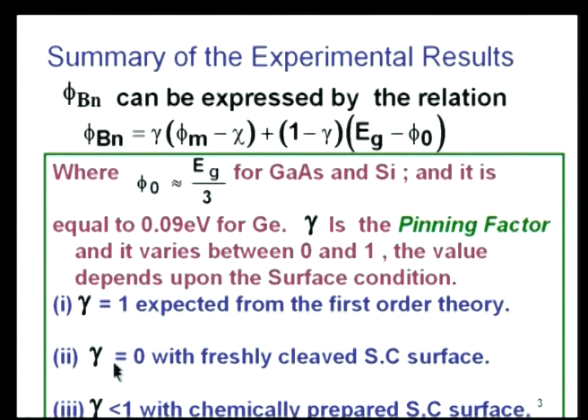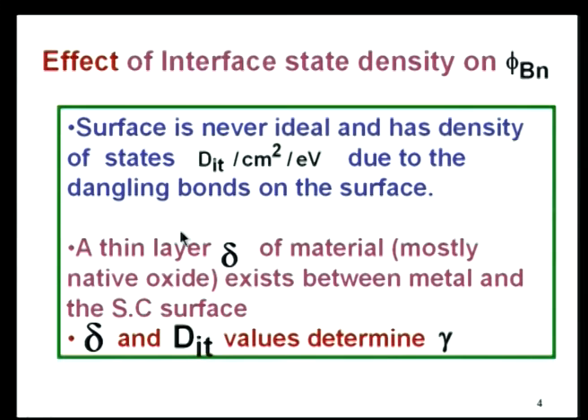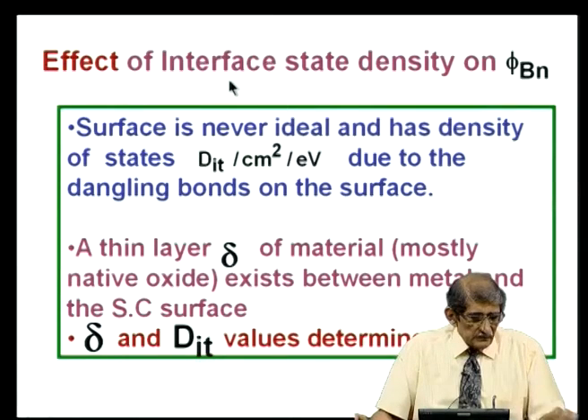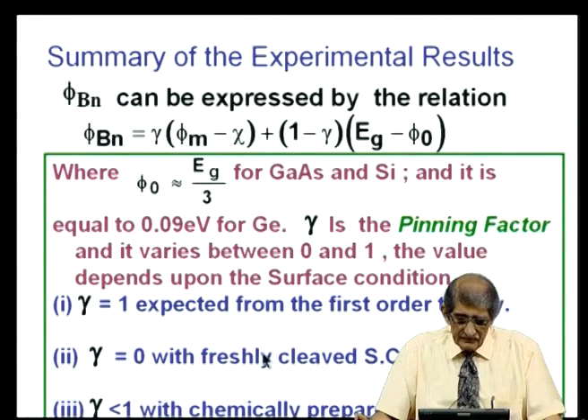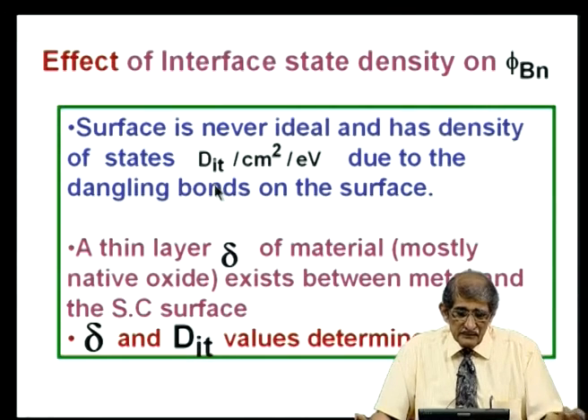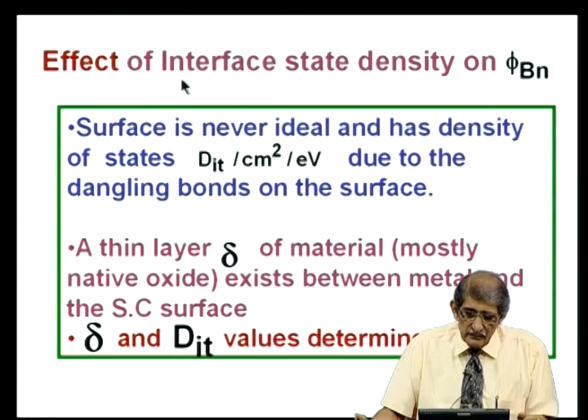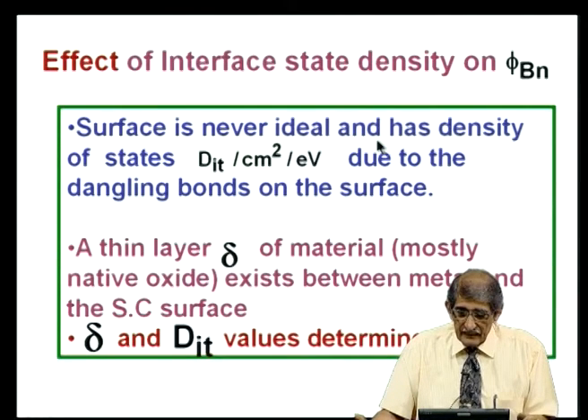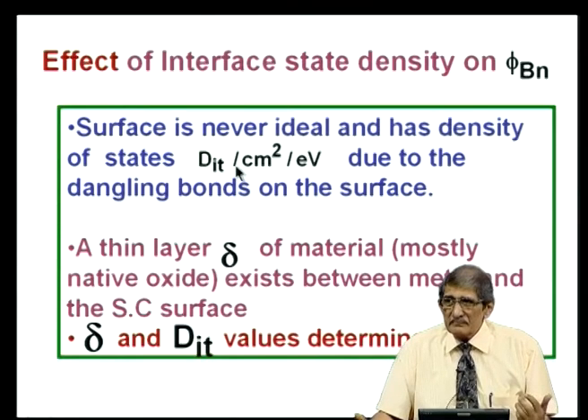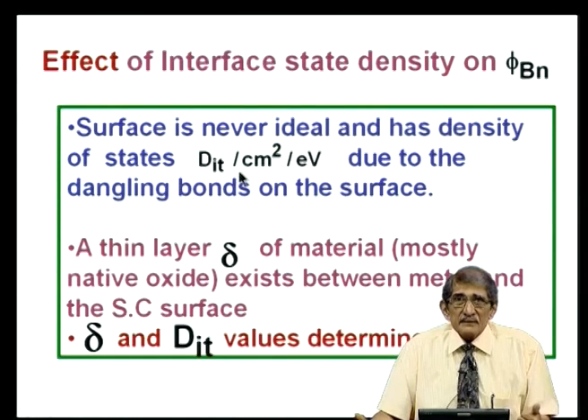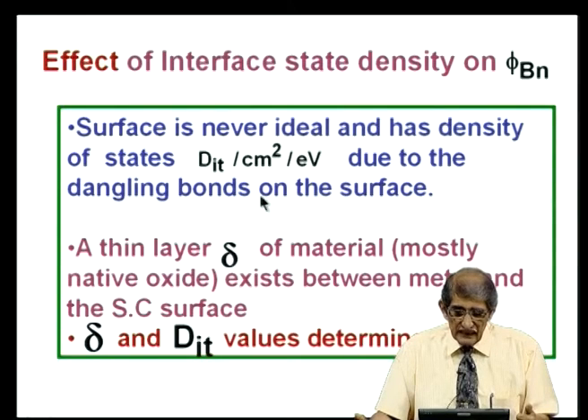When gamma is between 0 and 1, that is a chemically prepared surface, you get some variation with phi m, but not as much as phi m minus chi. Now, let us take a look at what happens there. Evidently, because in a freshly cleaved surface you get gamma equal to 0, or phi b n independent of the work function, it indicates that it is due to the surface state or interface state density. Surface is never ideal. The density of states is represented by D it per centimeter squared per electron volt, due to the dangling bonds on the surface.